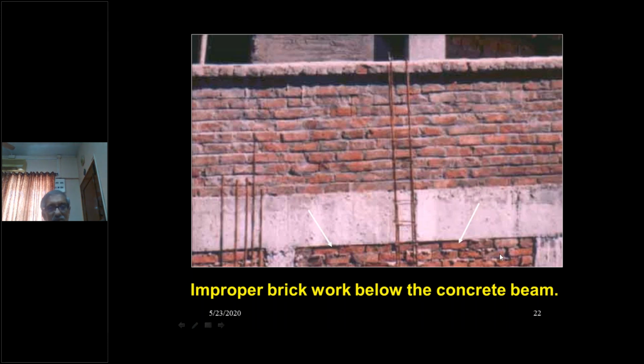So it's very, very important that when you are staying in a building where bricks and blocks are used to make walls, you must be very careful that before you do the plaster, you pack all these defective joints from the outside, because the water comes from the outside, not from the inside, and seal the cracks, cure them for at least 3 to 4 days or 7 days, and then do your first coat of plaster, and later on do your final coat of plaster.